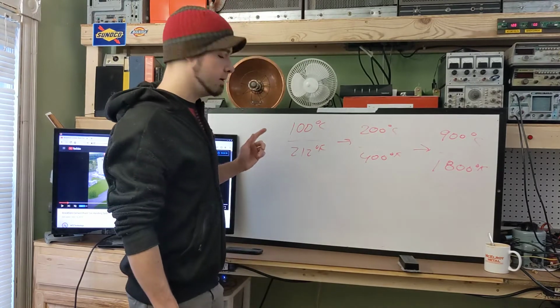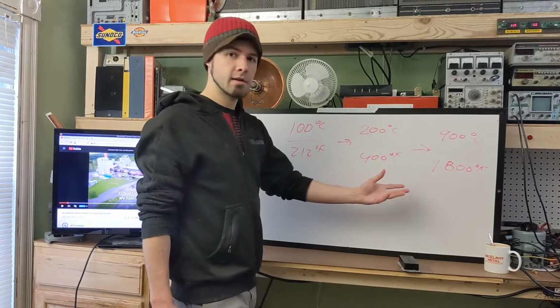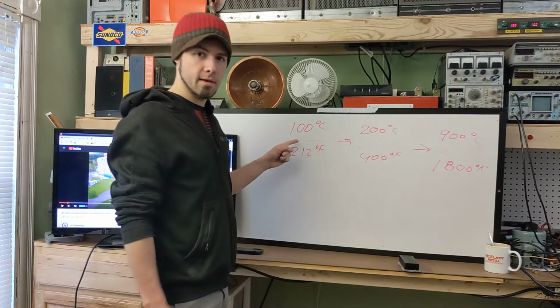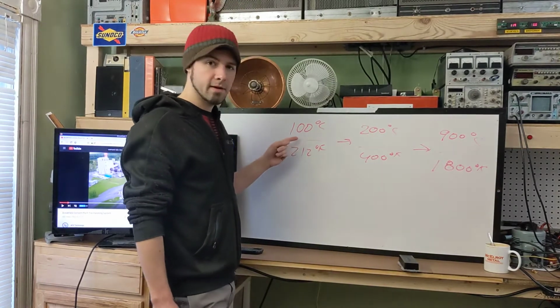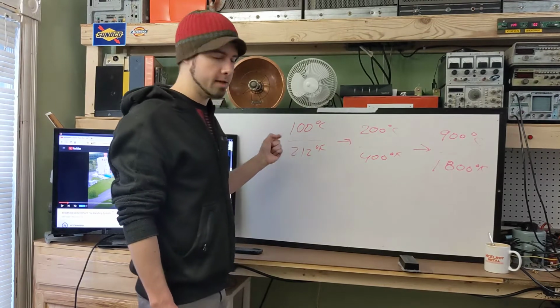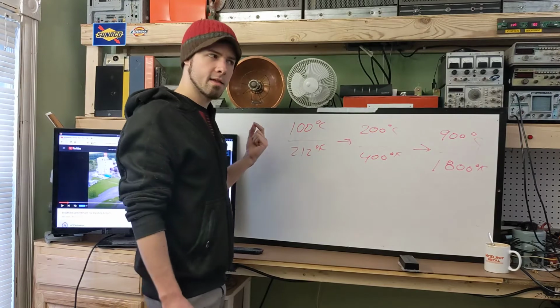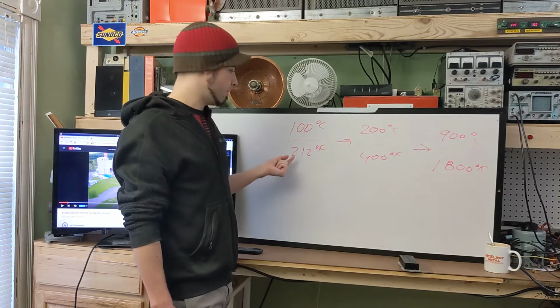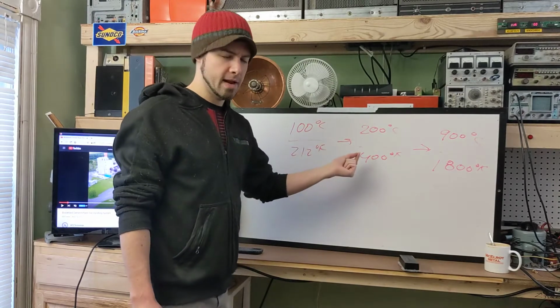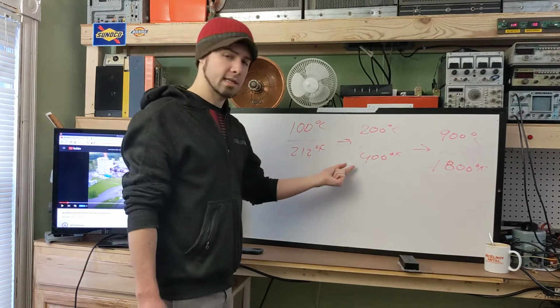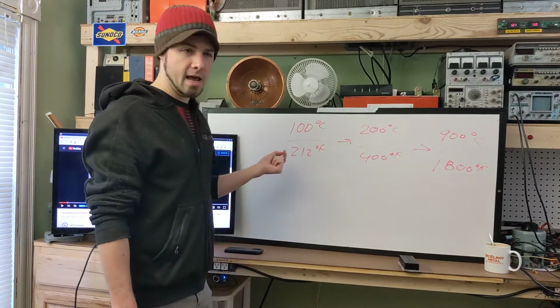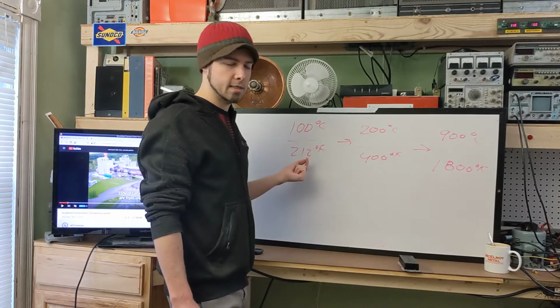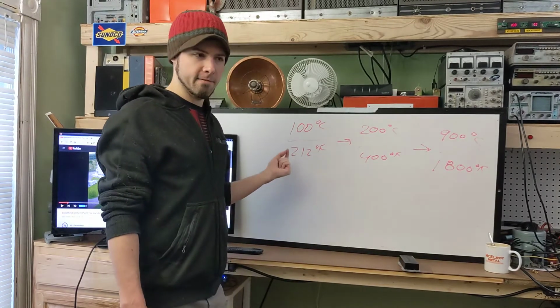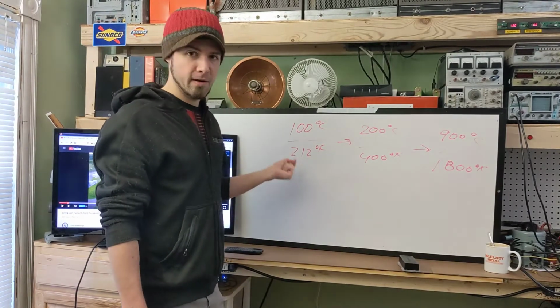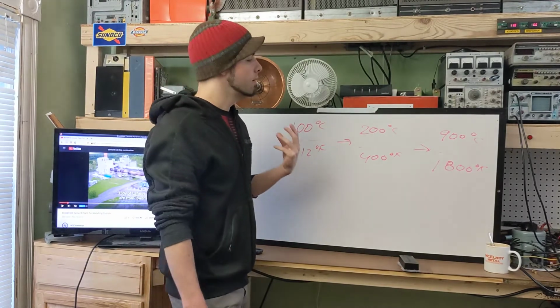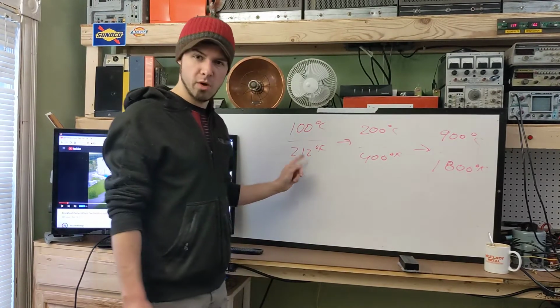That enables you to better utilize the energy, because if you were to just dump the incoming raw materials into a 2,650 degree furnace, you would be doing a process that can happen at 100 degrees Celsius or 212 Fahrenheit in an atmosphere that's 1450 Celsius or 2,600 degrees Fahrenheit. It's like using a baseball bat to swat a fly. It's far in excess of the force needed for the job, and it would be very wasteful of that very high grade, very high temperature heat to be just boiling off moisture.